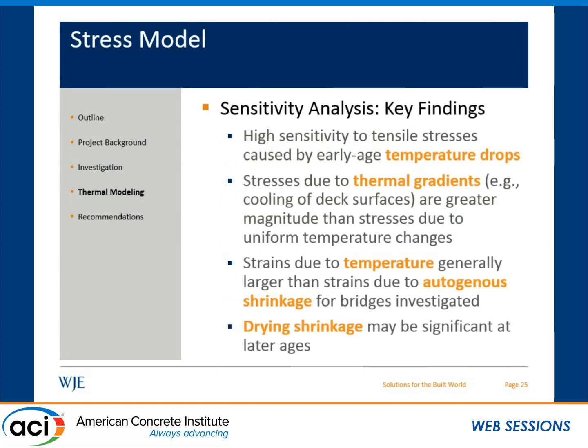And what our findings showed was a higher sensitivity to tensile stresses caused by early age temperature drops. That is, the initial temperature decrease from the hot temperatures of the concrete after hydration to the cooler ambient temperatures. The bridge deck stresses were very sensitive to that temperature drop and similar temperature drops.